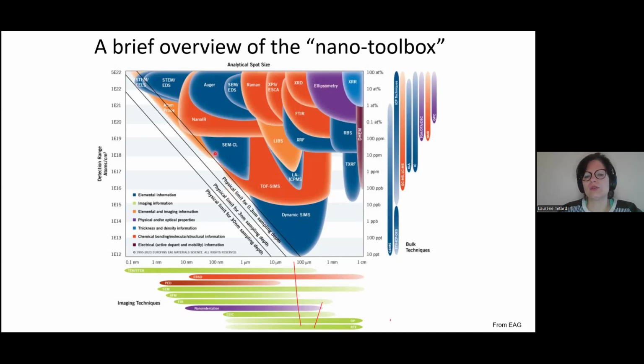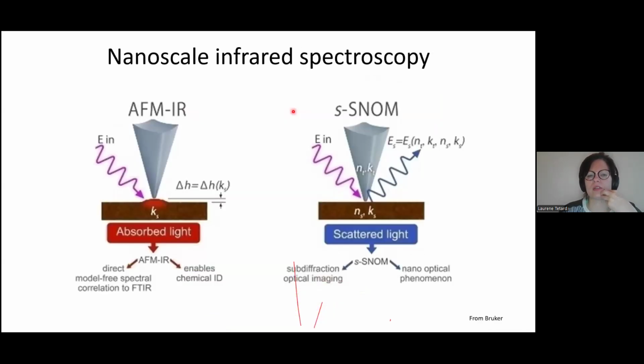So you see there are quite a few tools that are available, but NanoIR here is recently added to this chart, and so it's in the range of 10 to 100 nanometer spatial resolution with a pretty good sensitivity of the information, so you don't need a lot of material to get the chemical information. But this tool has the finer resolution, the AFM nanoscale resolution, of more commonly known techniques like Raman and FTIR spectroscopy that are infrared spectroscopies.